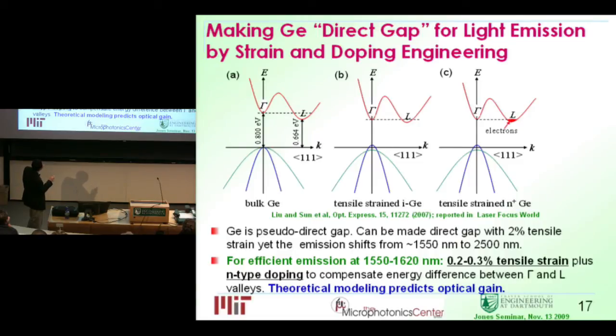That's no good. So our idea is actually to fill this bowl bottom with electrons by n-type doping. So now your bottom is filled to here. Now you imagine pouring water into this bowl. They will equally go to this gamma valley and this L valley. Okay, so this bowl is actually leaking because they recombine with holes here. The direct transition recombines much faster than the indirect transition.